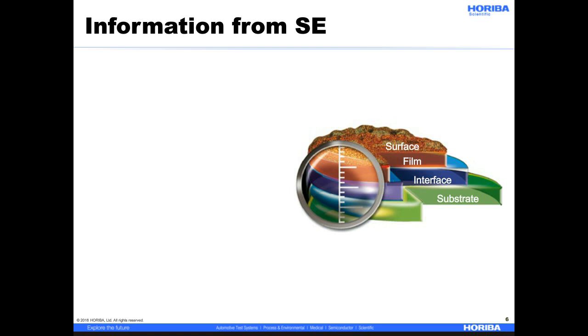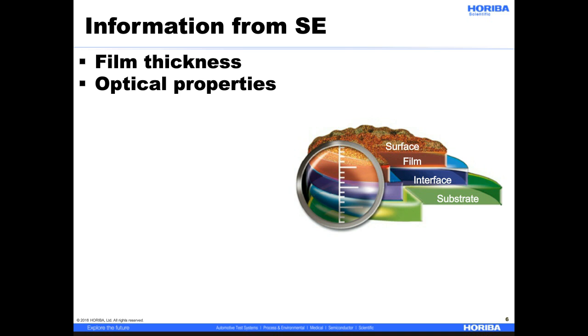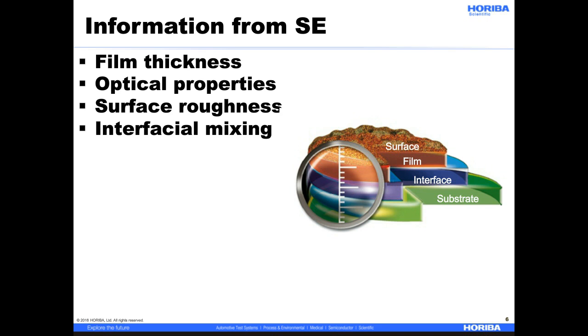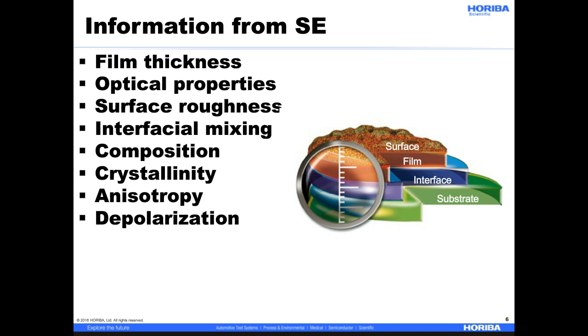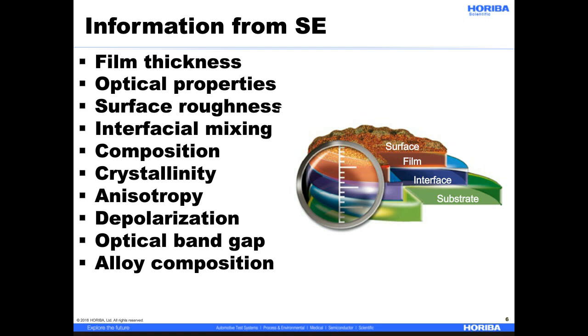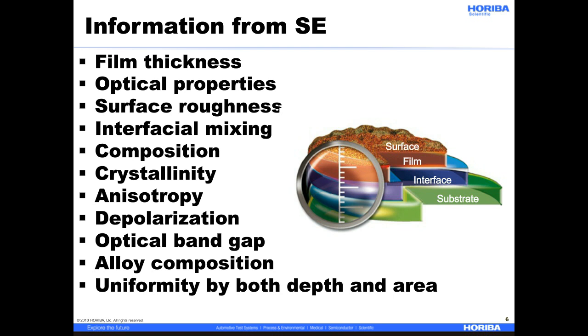So what information can we get from spectroscopic ellipsometry? The two most common things are film thickness and optical properties. But once you have the optical properties and you have the model, you can obtain surface roughness, interfacial mixing, composition, crystallinity, anisotropy, depolarization, optical bandgap, alloy composition, and uniformity by both depth and area. That would mean grading of index through the film, as well as mapping the sample to see changes in thickness and index.